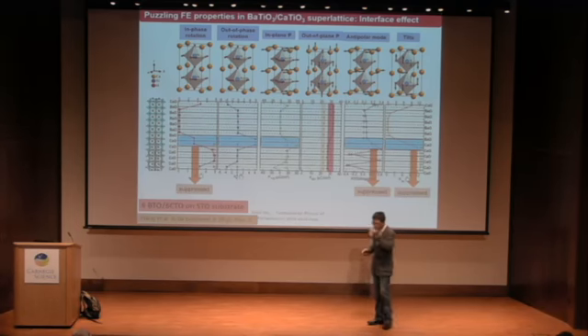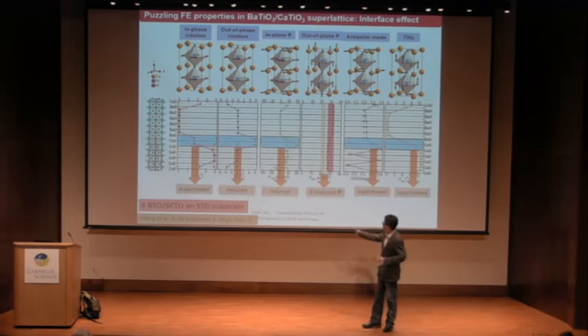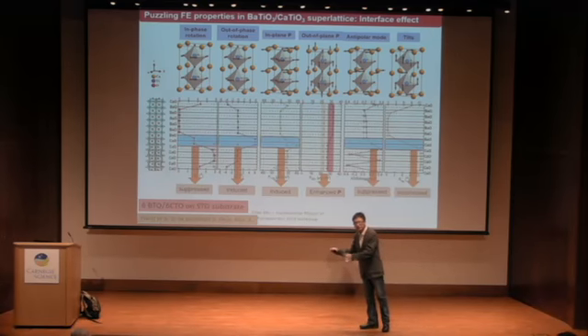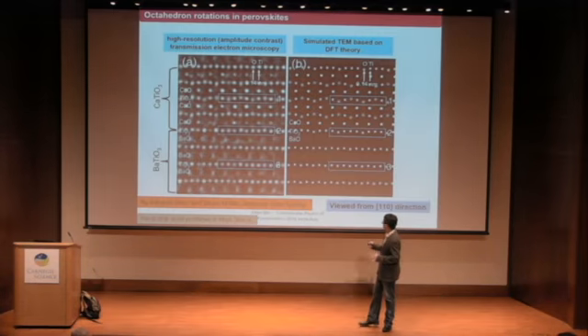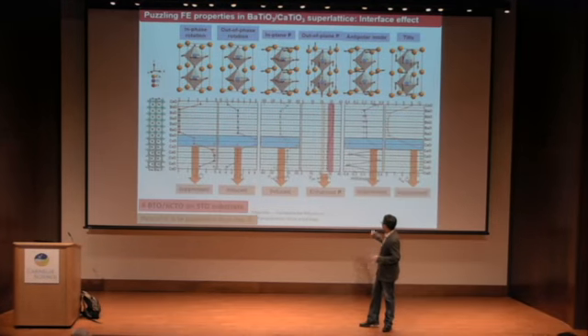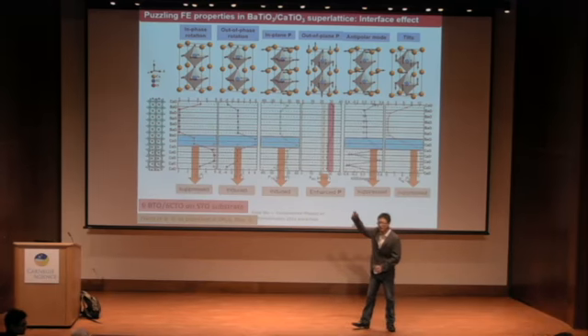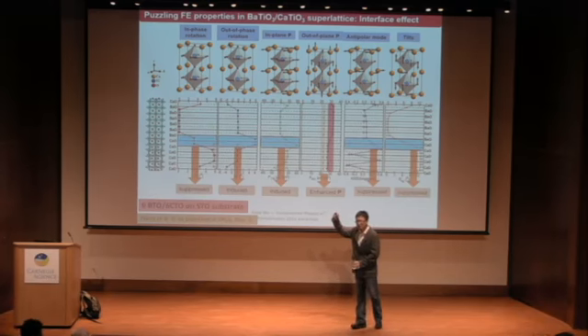Then what's new? We induce large out-of-phase rotations, which is typical for bismuth ferrite. And we also see an enhanced polarization around the 1,1,0 direction together. So due to this interface effect, this polarization along the 0,1 direction, which is measured by experiments by the way, 1,1,0 direction, is enhanced.